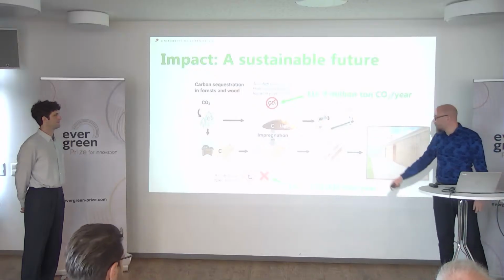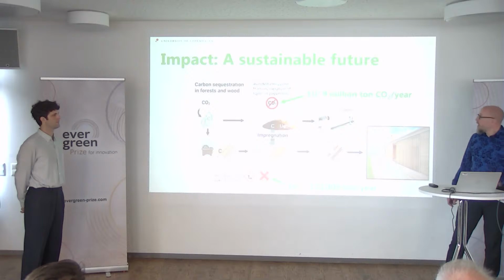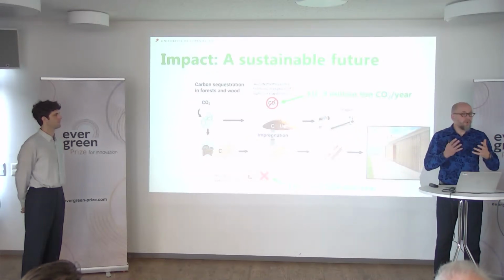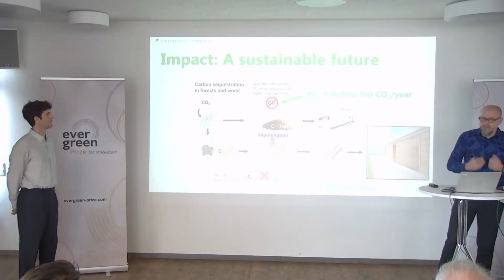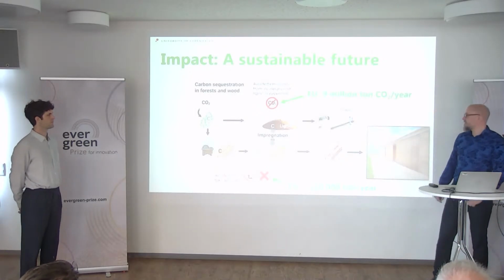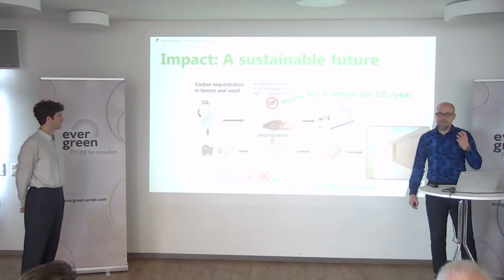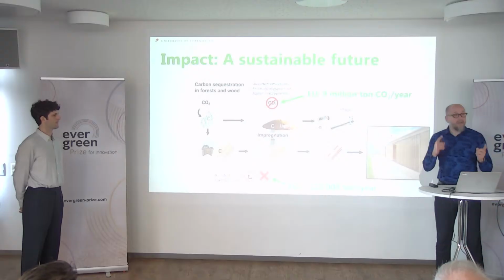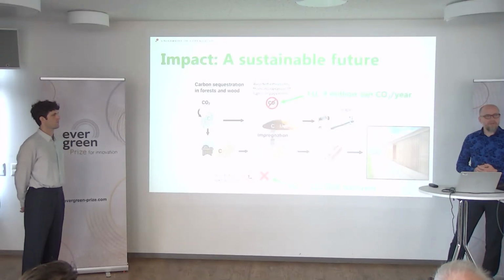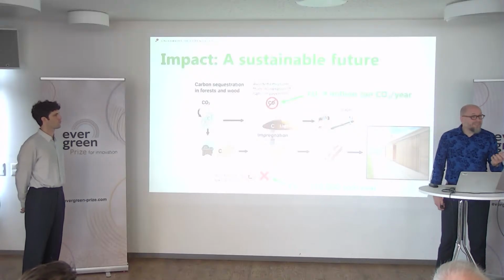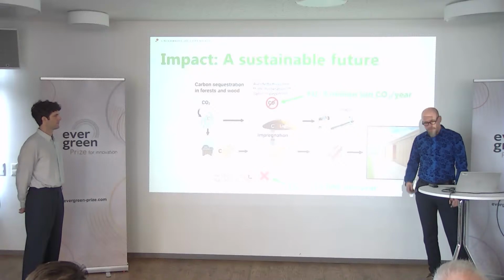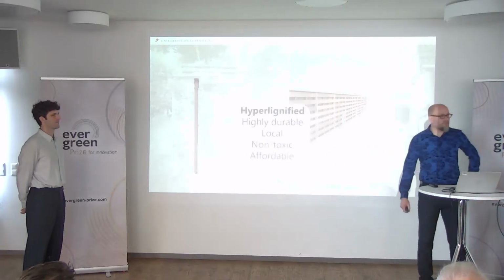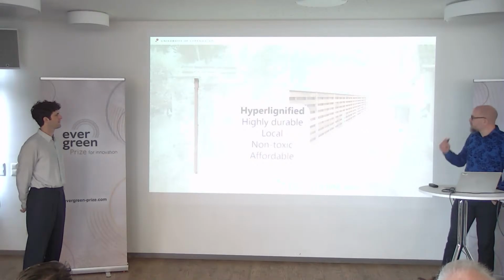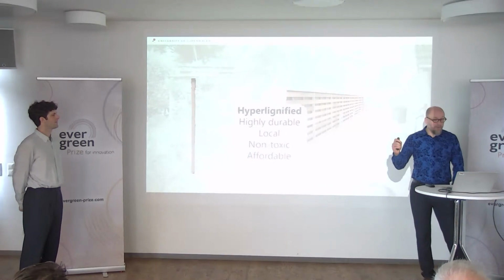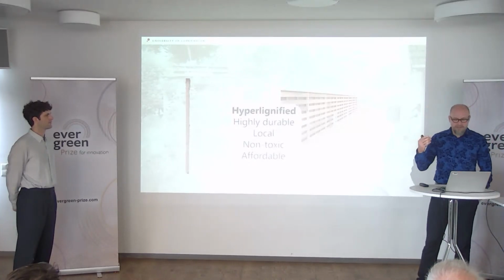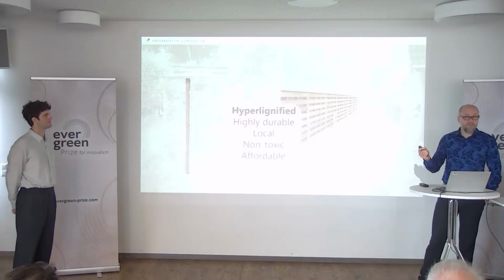Hereby avoiding using 120,000 tons of biocides every year as well as avoiding releasing millions of tons of CO2 from not burning the lignin in the paper mills, but instead taking it and embedding it in the wood by impregnation, supercharging the material with biogenic carbon that is kept in the lignin. So there's plenty of lignin to actually do this. And we'll end up with this hyperlignified durable wood product where we have both the carbon from the wood itself as well as the added carbon from the lignin. So hopefully, next time I have a construction project at home, I'll be able to choose a hyperlignified wood product that is highly durable, made from local wood, non-toxic, and affordable. That is the vision that we have. Thank you so much.